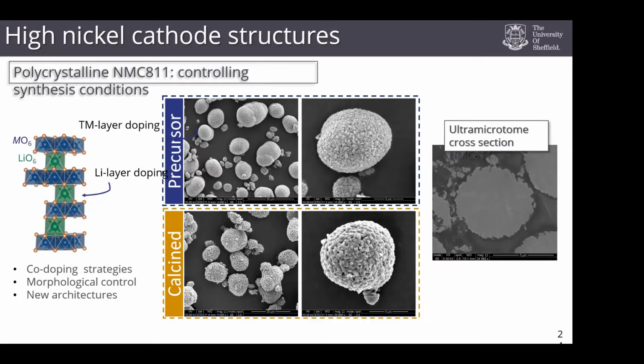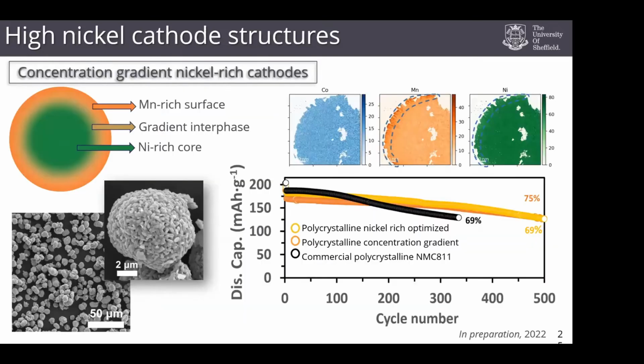And what we find is that although there's not as much lithium in there anymore, we get an awful lot more lifetime out of these batteries now, because we're keeping the structure, it's a more robust structure. The other thing we're doing, and this is another neat trick, is we can take particles that are nickel rich. So remember, this increase in nickel means an increase in energy density, but it can also mean an increase in side reactions that you don't want to happen.